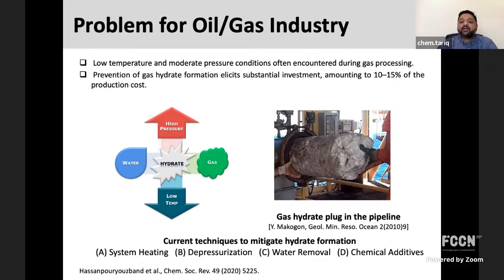There are different techniques to mitigate the formation of hydrates. One is system heating, where you cover or insulate the whole line so that you can raise the temperature so that hydrate cannot form. Then depressurization, so you depressurize the line so that you are always outside the boundary of hydrate formation. Sometimes water removal or dehydration is an option, and the last, and the most viable option, is the use of chemical additives which can inhibit hydrate formation.